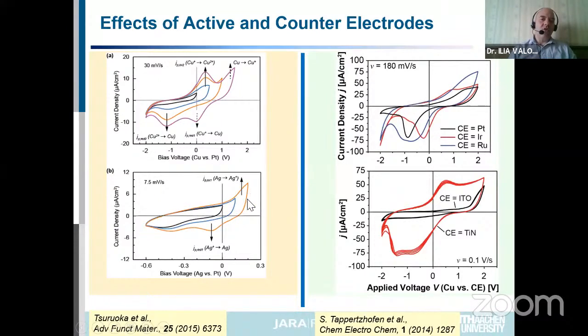So you need about 0.2, 0.3, and here you can 0.6. So this gives you an impression of the influence of the active electrode on the device behavior. The same applies for the counter electrode. The counter electrode is usually inert material, which is not directly reacting and is not providing any mobile ions. But its catalytic activity is important in that case, because it serves as a base that the filament can grow.